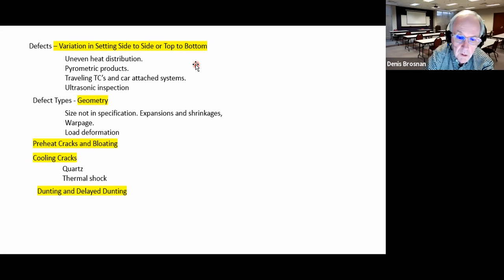That's really unusual. Sometimes additives are made to ceramic products to cause internal expansion during heating or firing. And sometimes those additives can be used to create specific pore size distributions. Some expansions take place, particularly in clay products, when calcium is added. And that's going to change the pore structure of the ceramics. And that's been a subject of much debate. We can also have warpage, load deformation. These are obvious things. Preheat cracks. Preheat cracks in most of the industries I've worked around are caused by heating too fast when some volume change takes place, like dehydroxylation. And that will form a crack within the ceramic.